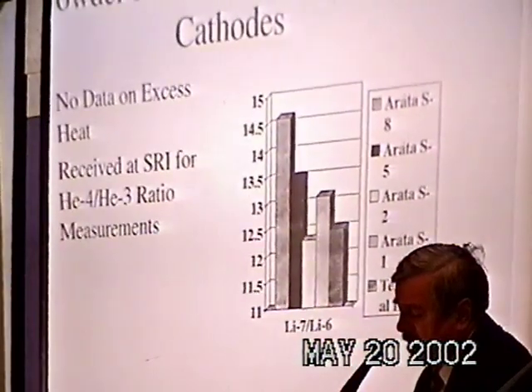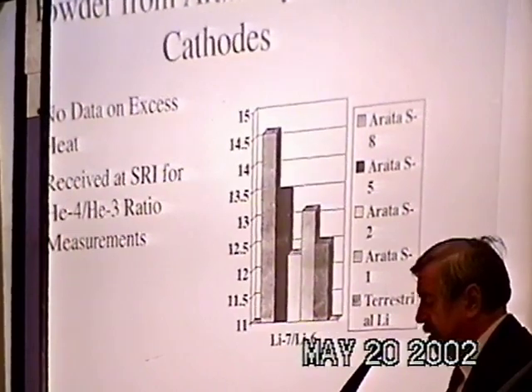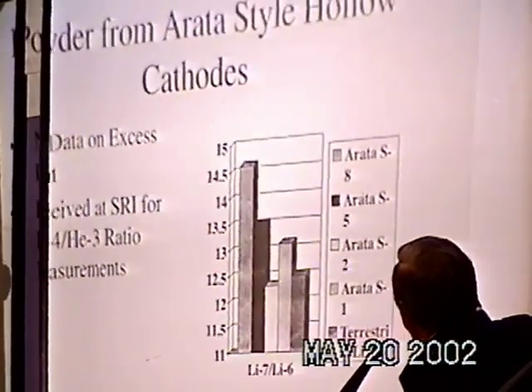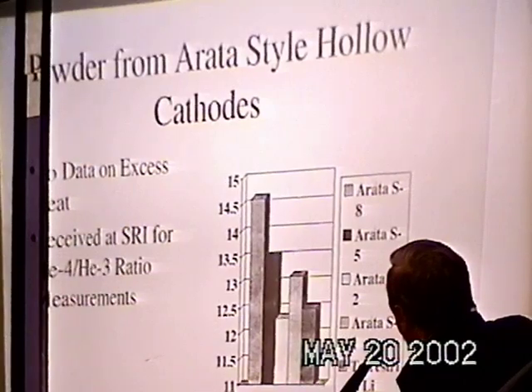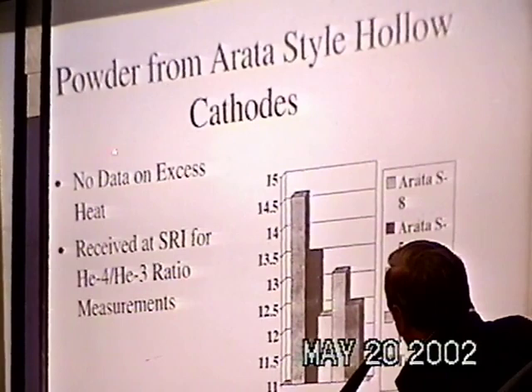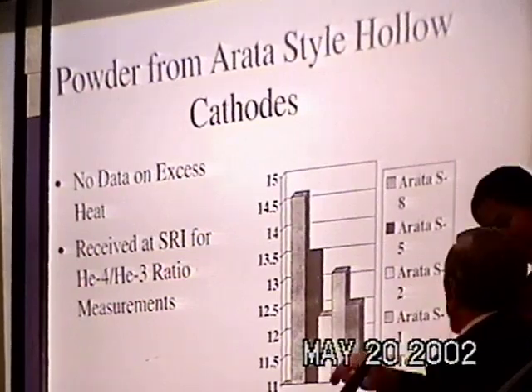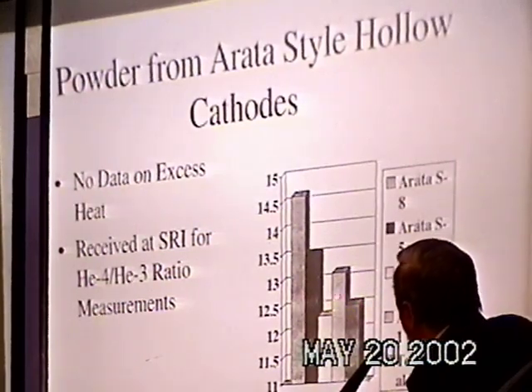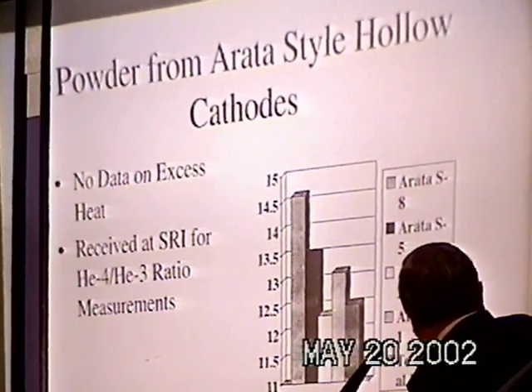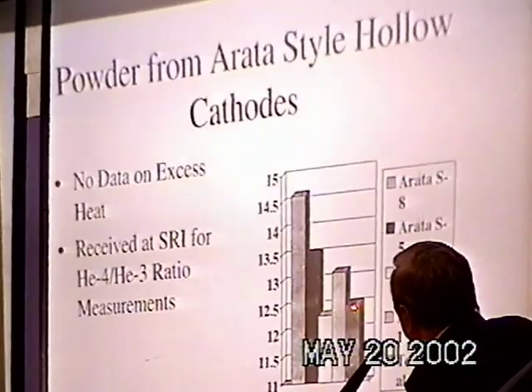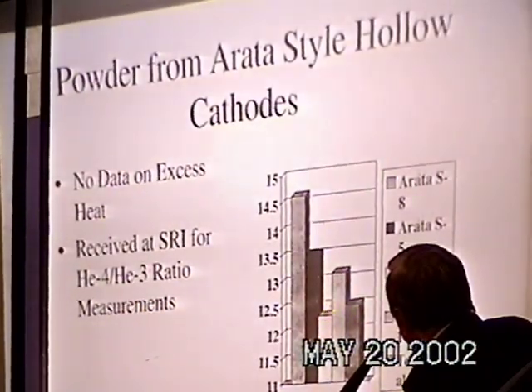And again, this is a set of powders from the Arata sent to Kubi to measure the helium-3-4 ratio. I don't have any data on these from the excess heat, but I assume that they were in an Arata-style cathode and did produce something. And this is the set of ratios that I got there. I have just designated 8, 5, 2, and 1 and terrestrial lithium. You can see that here's one that's a little below, but all the others have a slight increase over that of terrestrial lithium. So the hypothesis is still alive, but it's taking a few body blows.